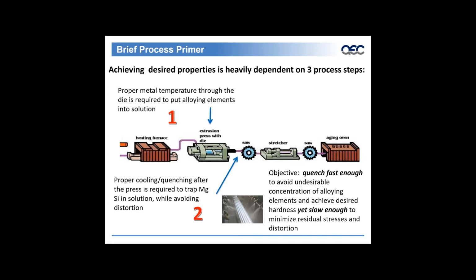Also, as we mentioned with the 6082, it's a higher mag silicon alloy, so the production rate is reduced as a result of the material flow through the extrusion die. But the quench process here is critical for the microstructure, it's also critical for tolerance, and it's also critical for performance, productivity.